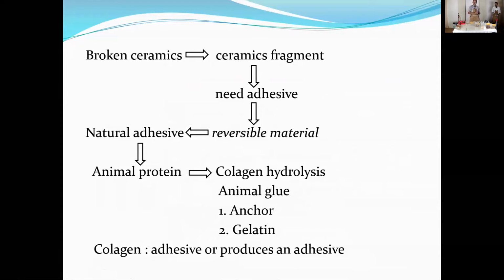As I said before, the use of anchor in ceramic is necessary because this material is reversible. So when a mistake happened during the attachment of the fragments, the attached fragments can be detached without causing damages on the fragments itself. And it will not leave any residue on the surfaces of the fragments.